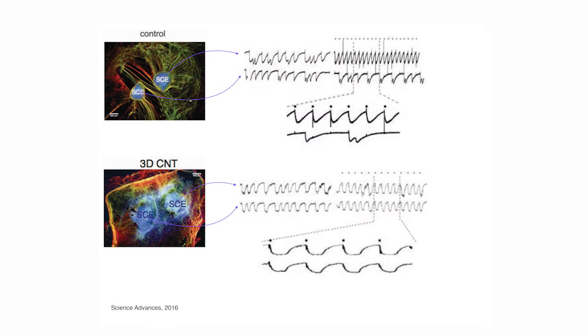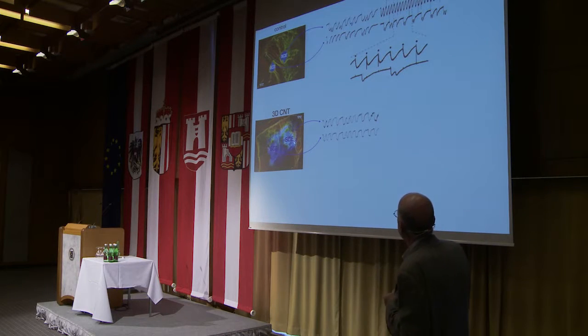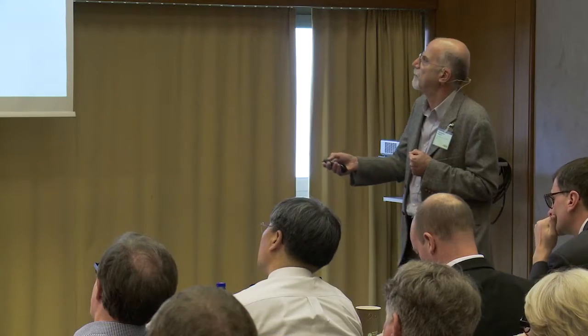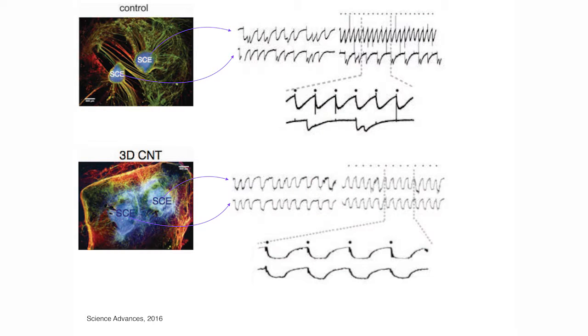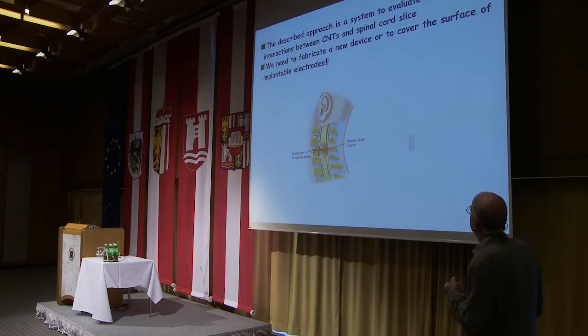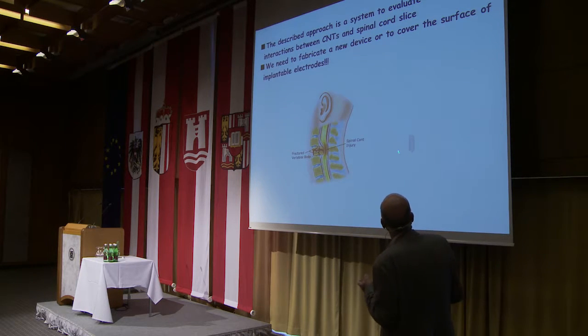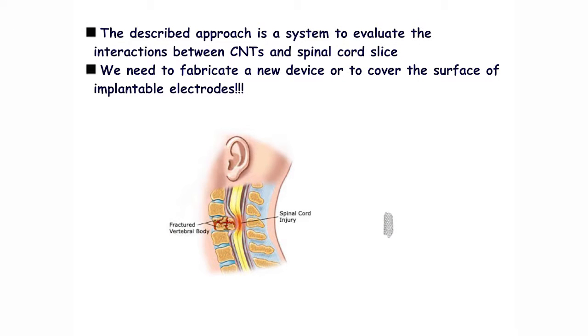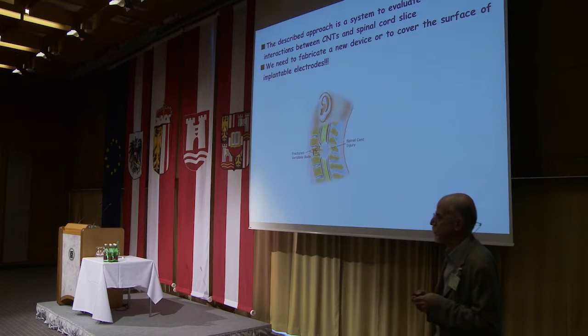In the case of carbon nanotubes, we see that already at the stage of spontaneous activity, we have a perfect correspondence of the signals. And if you stimulate one slice with regular pulses, then we can see that the other one responds very efficiently. So this means that the two slices now are completely electrically connected. And this is, of course, very promising in terms of what we want to explore, because now what we are doing, we are placing the device in the spinal cord of the lesioned animal and see whether this approach will work or not.